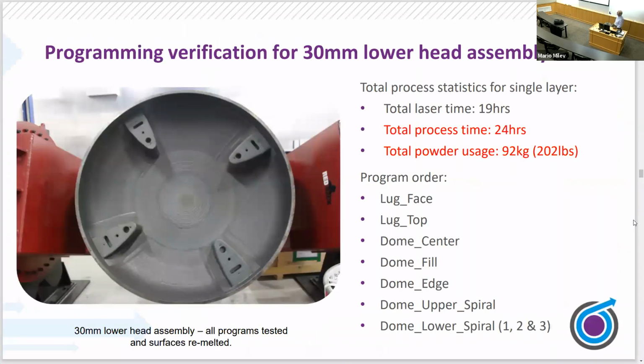Again, this is being done at the Nuclear Advanced Manufacturing Center. There were probably 8 or so different programs that we had to develop to actually weld this component, but we fully automated the process. You could go out today and utilize that to clad an inside of a reactor. This was a very difficult, complex problem, but computerization obviously allowed us to do that. We've reduced the time to do this to about 24 hours from probably, again, about a 2-week cladding process. So that, again, is a pretty big game changer.